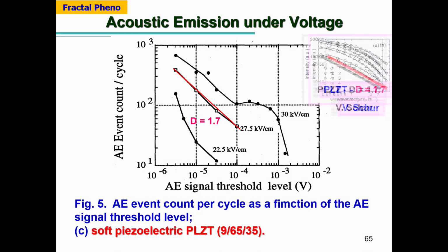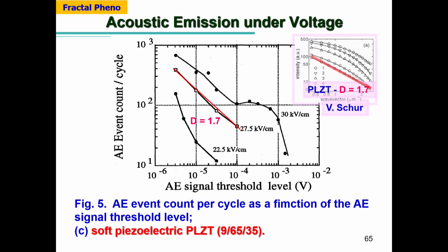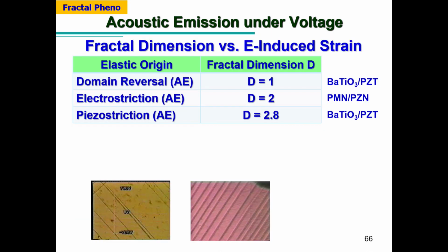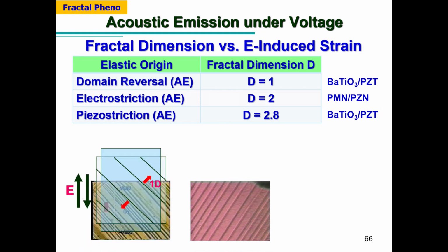And if you remember Dr. Schur's result, 1.7, accidentally exactly the same value, okay? So this is the final summary. Domain reversal: fractal dimension is 1. As you remember, the domain is moving one-dimensionally. Therefore, it seems this AE origin is one-dimensional motion, okay?